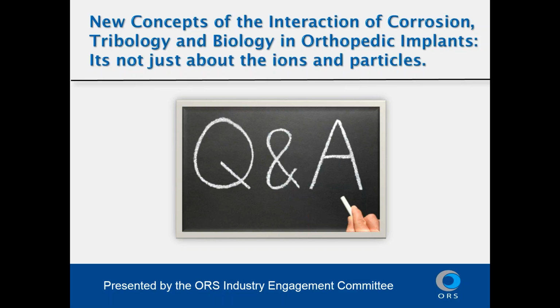Okay, second to last question. Is there any correlation between implant infections and cellular-based corrosion of metal implants? Yeah, so we have not been able to do that study to look at retrieved implants with infection and try to correlate inflammatory cell-induced corrosion with the infections. I would venture to say that it's quite possible. I do know that this recent paper that came out confirming ICI corrosion in a separate retrieval program did note that there was a correlation between the presence of adverse local tissue reaction and the presence of inflammatory cell-induced corrosion in the pool of retrievals that they investigated. And so I think there is a pretty good indicator that the severity of the patient's reaction correlates with the presence of this type of corrosion.